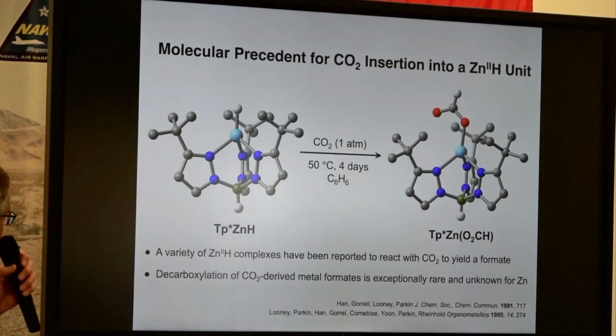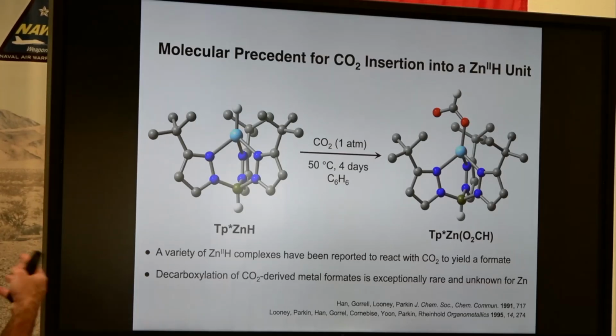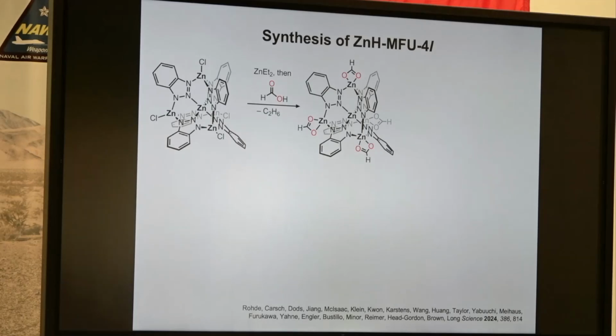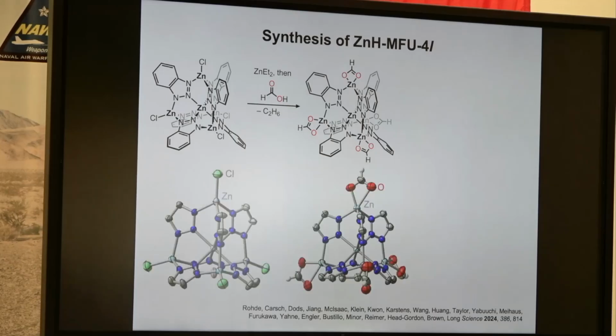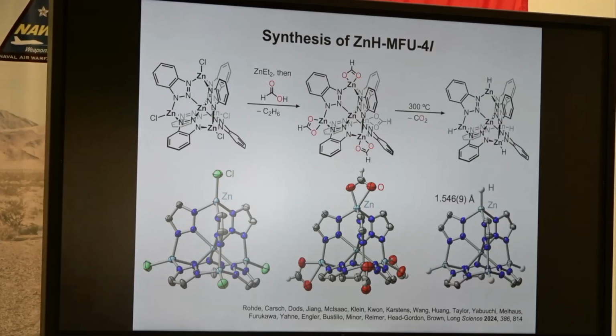And one reaction that these kinds of molecules can do is if you replace the chloride with a hydride, that hydride will sluggishly react with CO2 to make formate. Right? And the reverse hadn't been shown, but you can see it takes quite a while to make the formate. Well, we can make this in a MOF. So first step, we're going to replace the chloride with formate, which is just a ligand substitution, and here's the crystal structure. And then if you heat that formate, you can release CO2 and make the hydride. And here's the structure of the hydride. You can see that short 1.5 angstrom zinc-hydrogen bond distance.